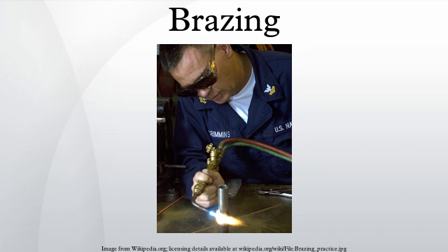Filler metals. Some brazes come in the form of trifoils, laminated foils of a carrier metal clad with a layer of braze at each side. The center metal is often copper. Its role is to act as a carrier for the alloy, to absorb mechanical stresses due to, for example, differential thermal expansion of dissimilar materials, and to act as a diffusion barrier.